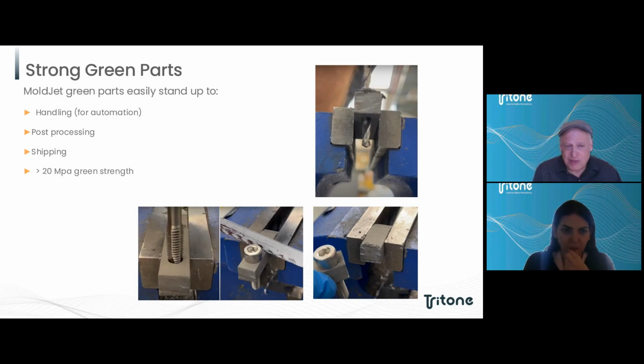And the number is 20 megapascals. Greater than 20 megapascals is the actual measured value, which compares typically to 5 to 7 megapascals, the numbers I've seen for competing technologies. But we show here just the fact that you can chuck it up in a vise and drill and tap holes and cut parts, and even here, just chucking a part up in a vise would crush most parts. Forget about cutting it. You wouldn't even be able to hold it in a vise. And so, if we had live video, we could show this, but the point here, I think, is made. The toughness of the green parts is something that allows our customers to contemplate higher volume manufacturing, and simultaneously, it's not magic. It all comes from the fact that the parts are denser.